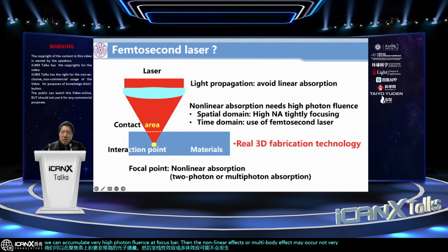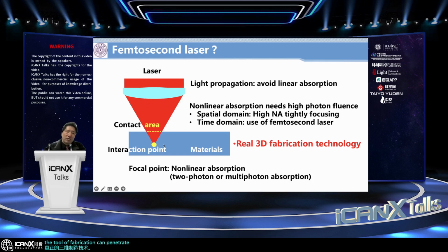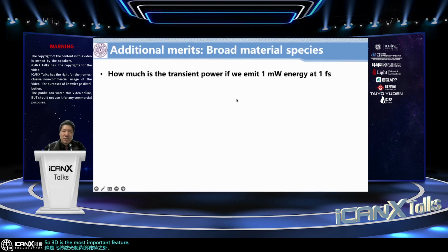So by doing these two points, first we choose a wavelength to avoid linear absorption. Then we focus the laser to excite material using the nonlinear effect. Then we realize the world's first real 3D fabrication technology. The tool of fabrication can penetrate into materials and get nanoscale features of fabrication. This is the unique point of the femtosecond laser fabrication. So 3D is the most important feature of this technology.